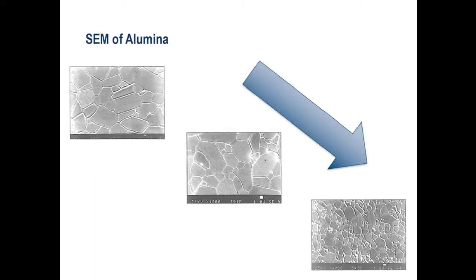You can see on the slide now some SEM images of alumina ceramics. Even though alumina has been used since the 1970s, the manufacturing process has changed dramatically. You can see the SEM image on the top is an SEM of a first generation alumina ceramic used in hip replacements. The middle image is from the second generation, and the third image is from the third generation isostatic hip ceramic materials. And you can see that the grain size is getting smaller and more uniform.